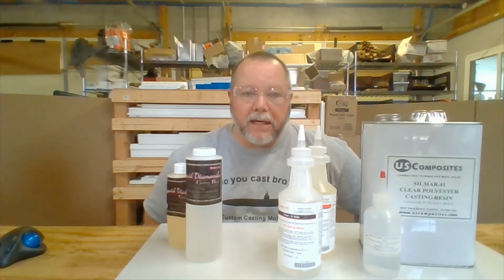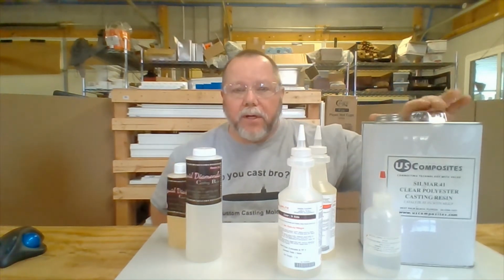MEKP is added, which basically is an oxidizer, which then heats up the resin, and heat causes it to cure. And so the more MEKP you put in it, the more oxidation takes place, the more heat that's developed, and the faster it cures. So when I cast with polyester resin in Silmar 41, I usually cast with about 3, sometimes 4 drops per ounce.